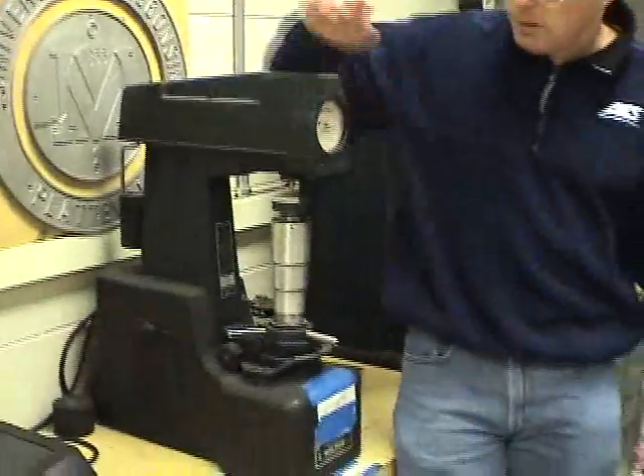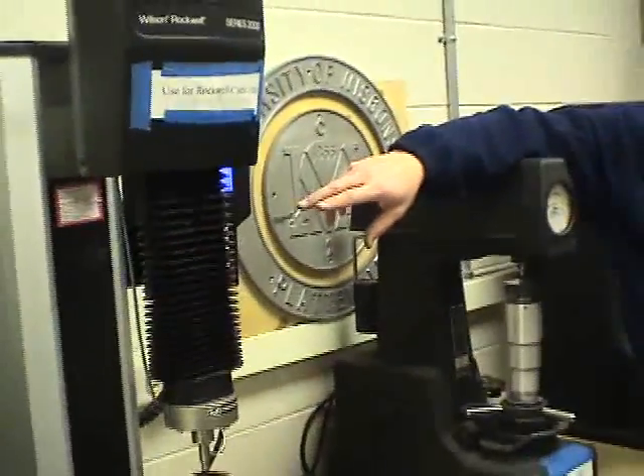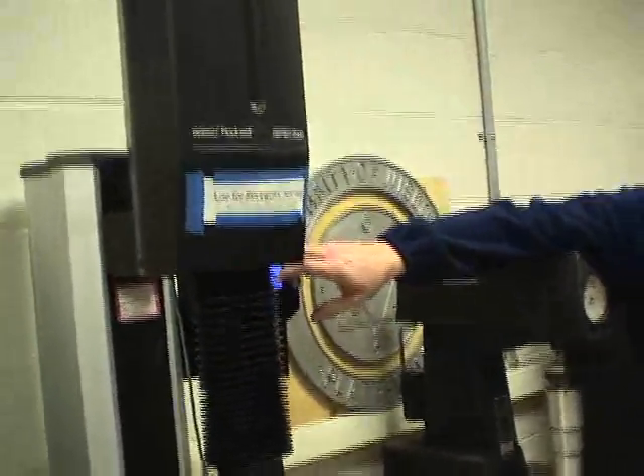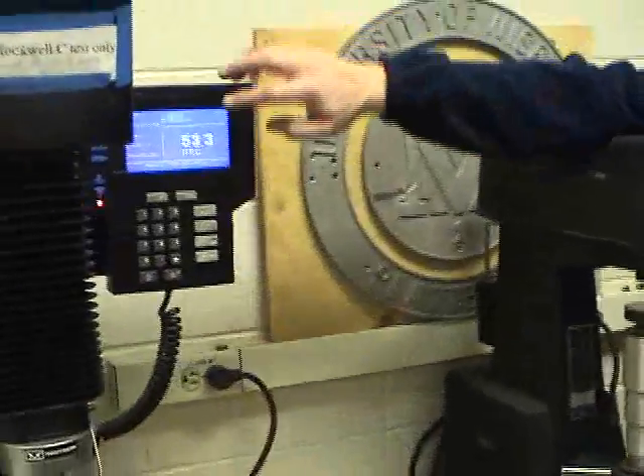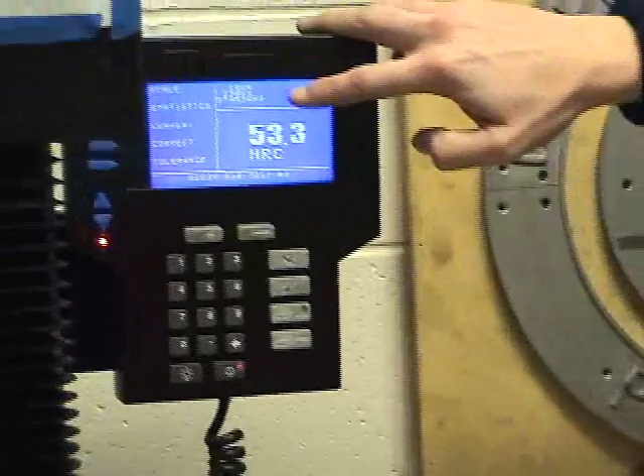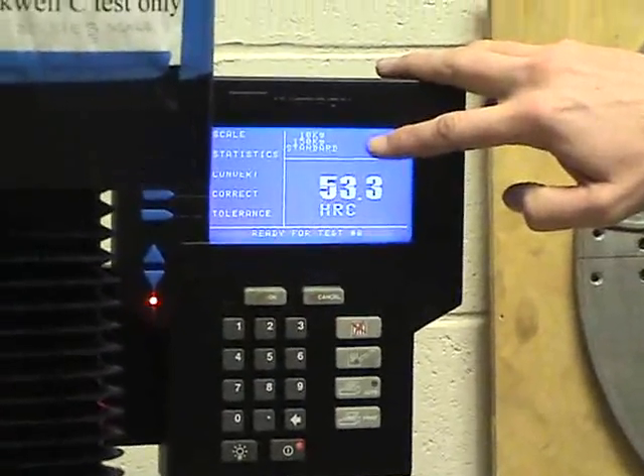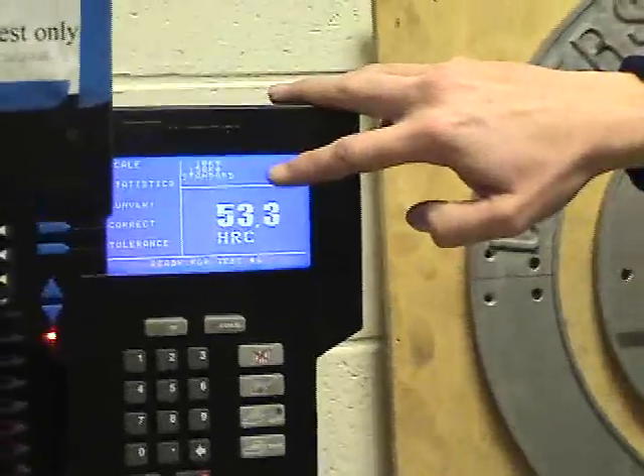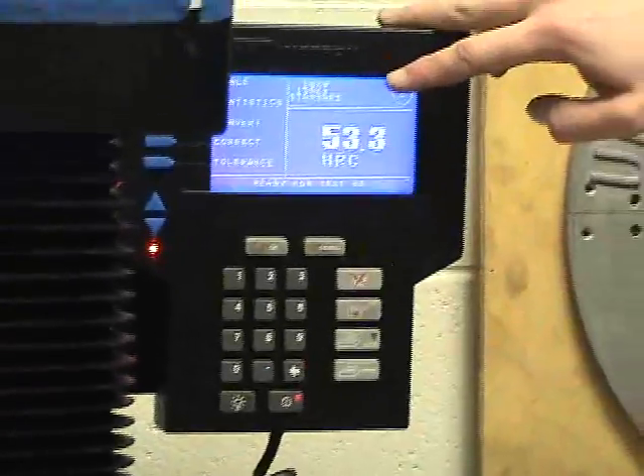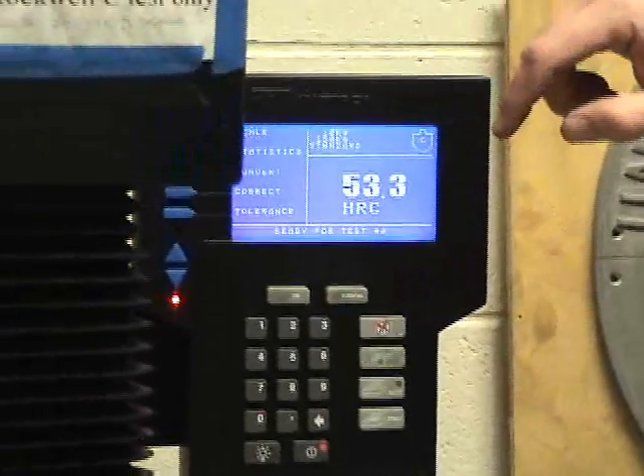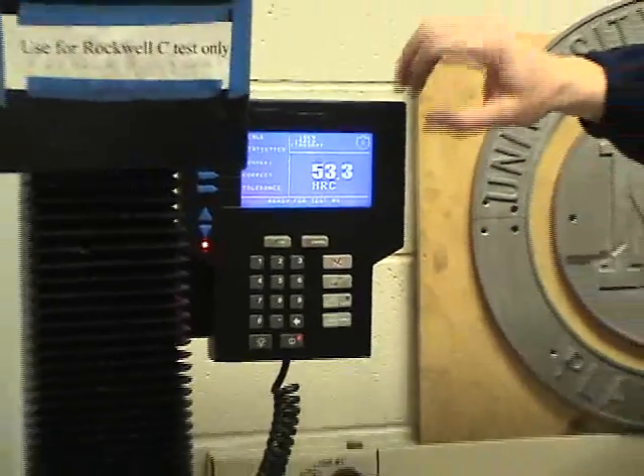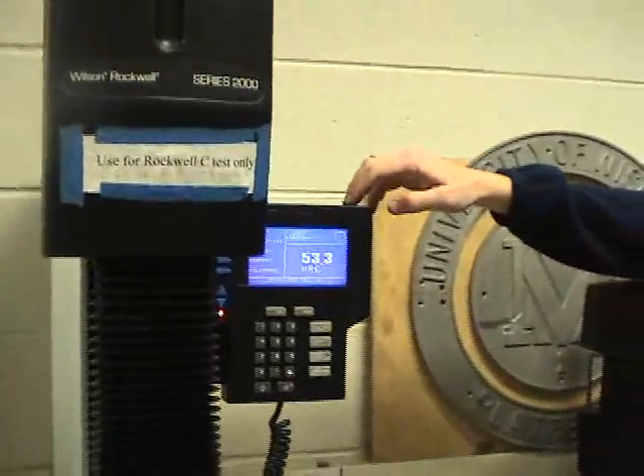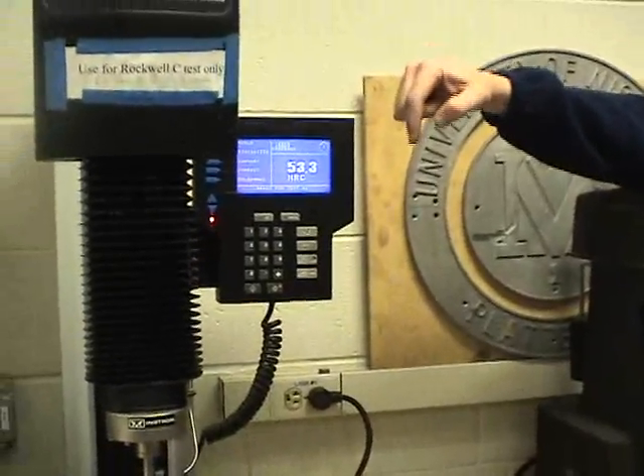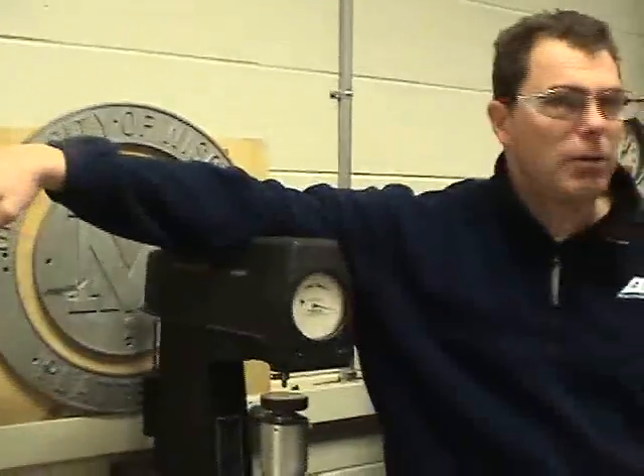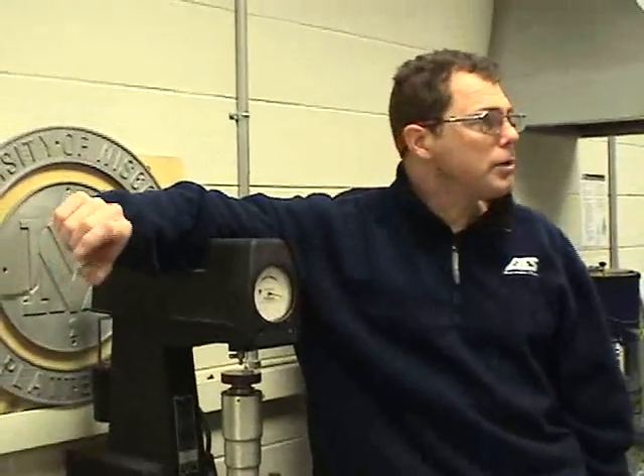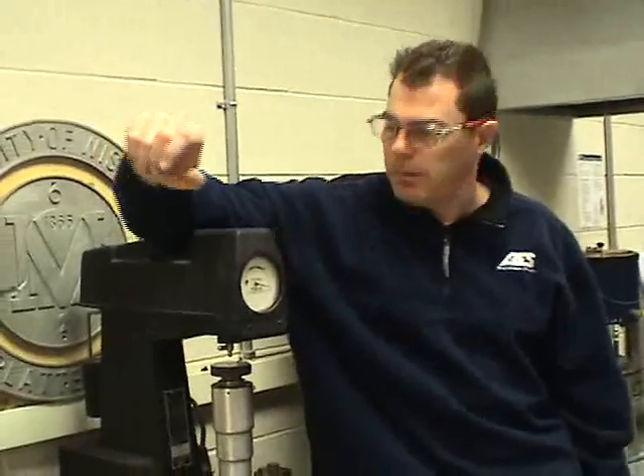And then this particular test will put 150 kilograms. It'll first put 10 kilograms. It says right here, 10 kilograms preload on it. It'll come down and put a 10 kilogram preload, and then it'll put 150 kilograms, like 300 pounds, on that little diamond. So it will push it into the surface of this piece of steel. If it's hard, it won't go in very far. If it's soft, it'll sink in deeper. And it has a very accurate scale inside, a micrometer scale that it measures. Now in this case it's electronic. It measures how deep that indenter actually sunk between 10 and 150 kilograms. And that's how it measures the hardness, is that depth of penetration.